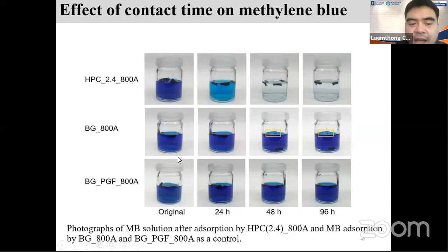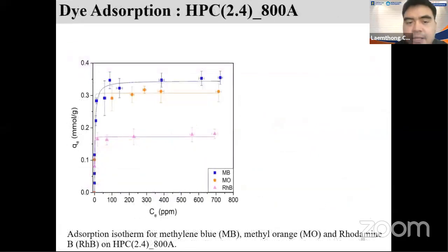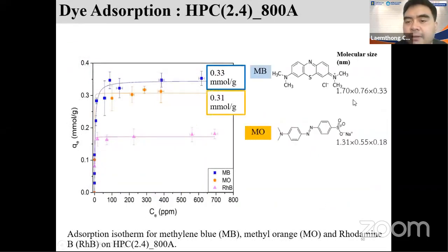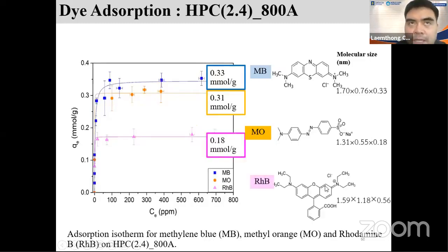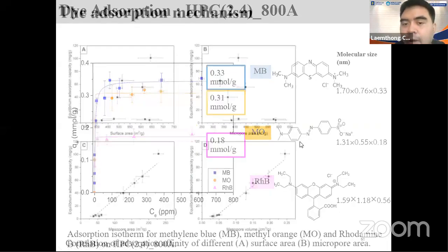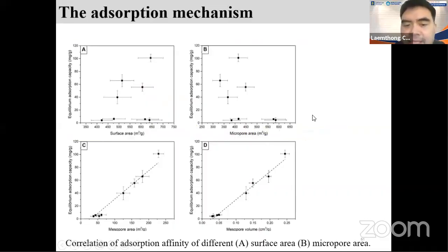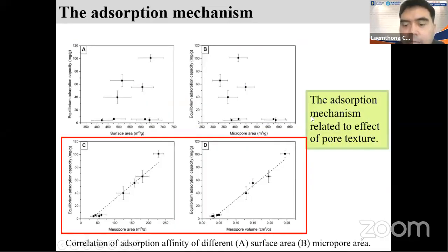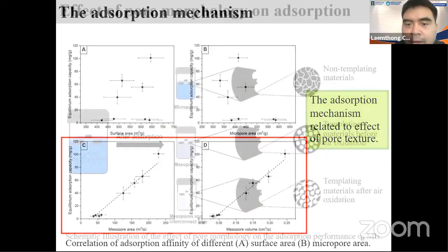Compared to the other activated carbon that I made in the other way, you can see that they don't adsorb. But we relate this property to the porosity. Because methylene blue has quite a big size, similar to MO or methyl orange, compared to rhodamine B, which is actually two times bigger than methylene blue and methyl orange. But still they can adsorb quite well. And we can see that the mesoporosity actually influences this. So we can continue our project on this kind of mesoporosity in our product.